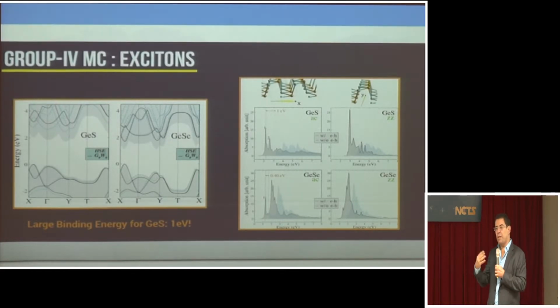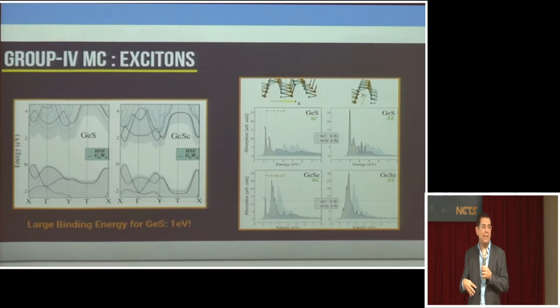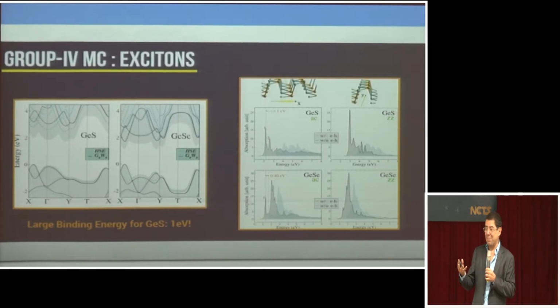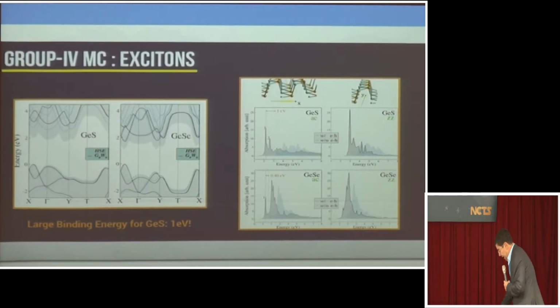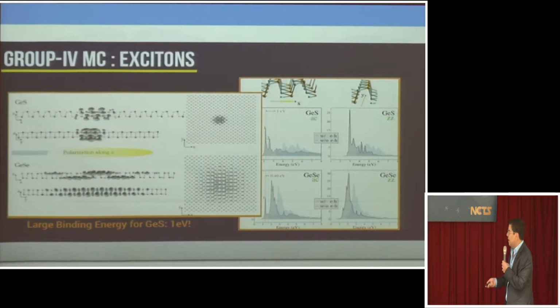Okay? So if you want to understand the optical absorption of these materials, you really have to do something better than traditional band structure calculations. In fact, these calculations, if you do GW, which by the way, people who do computational physics know, is enormous in computer time compared to any DFT, but it's essential, it's fundamental if you're trying to understand things like optical absorption, because of this enhancement of the electron-electron interactions.